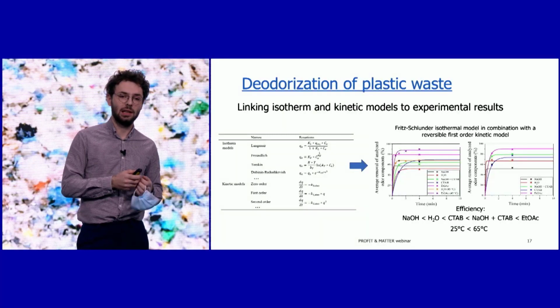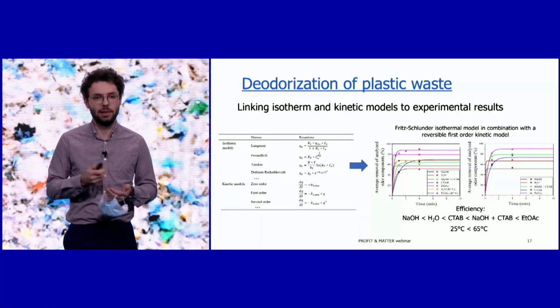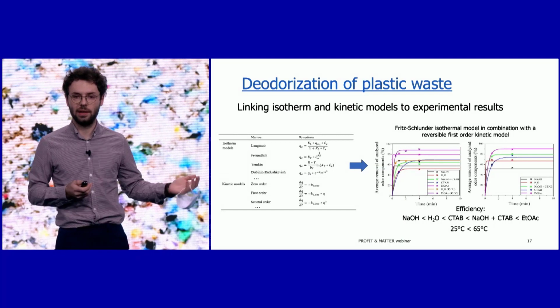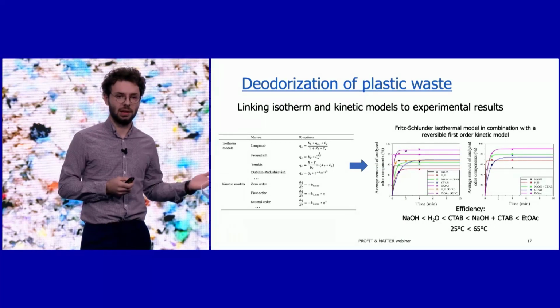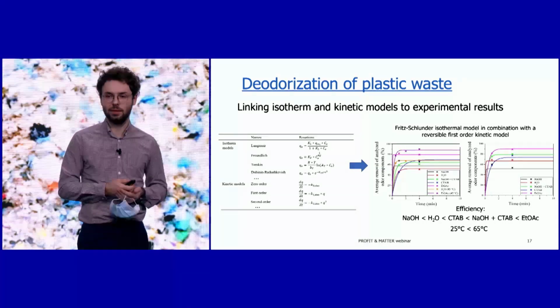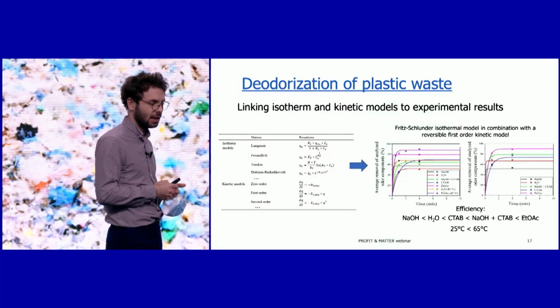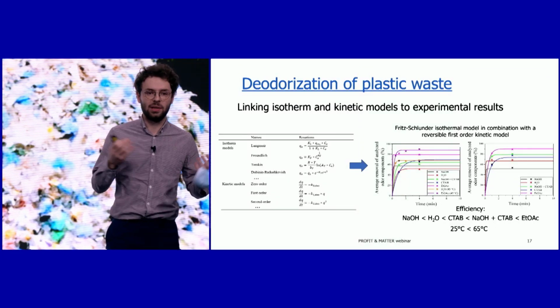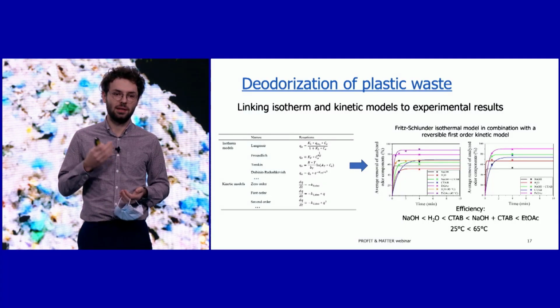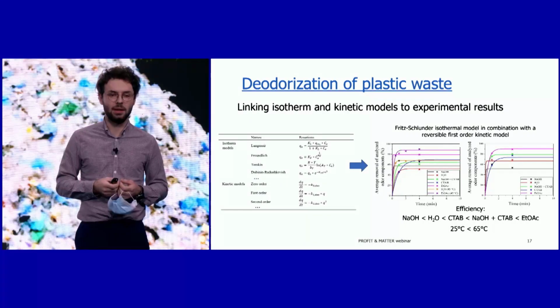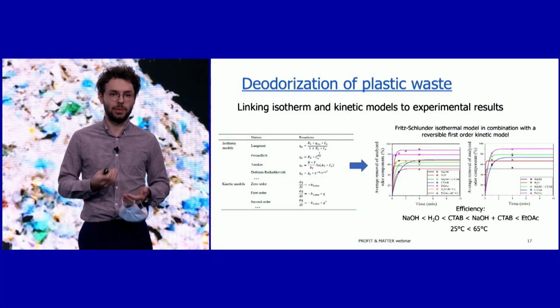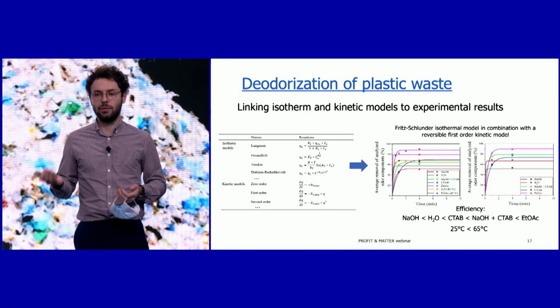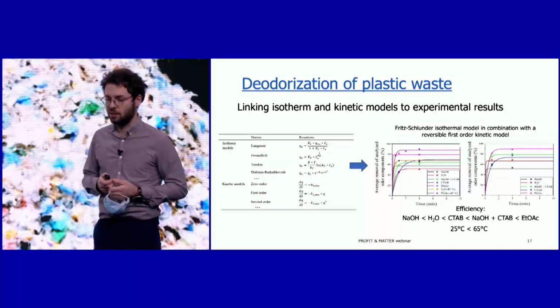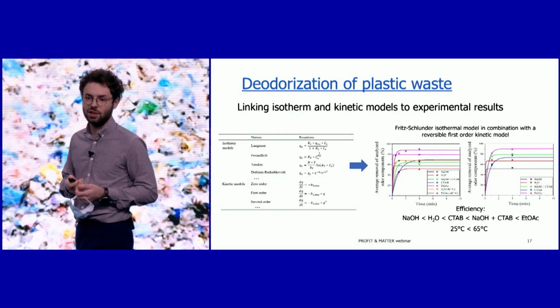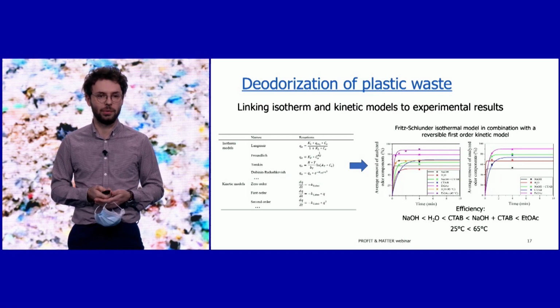Another thing that we saw is that the higher the temperature, the better the deodorization. So 65 degrees Celsius gave better results than, for instance, 25 degrees Celsius. These things can be explained by considering the deodorization process as a solid-liquid extraction process. Typically, such a process is influenced by the polarity of the extraction medium and by the temperature, which is also what we saw for deodorization.